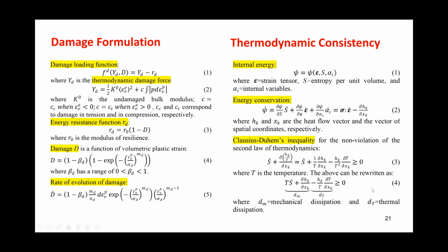Let's talk about thermodynamic consistency. That's an important component of the model. The internal energy of the material is composed of the strain tensor epsilon, S the entropy, and some internal variables. If we take the time rate of this, we could show that the rate of change in the internal energy is equal to the product of the trace of the stress tensor and the strain rate tensor minus the derivative with respect to the coordinates x_i of the heat flow. Okay, so the work done by the stress multiplied by the strain rate is countered by the change in the heat flow in the material.